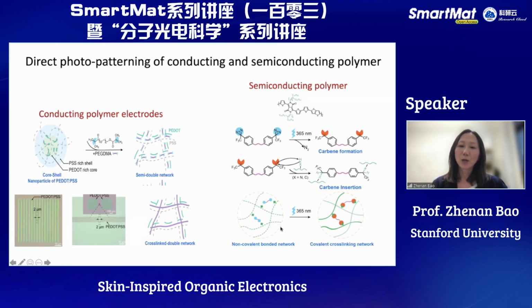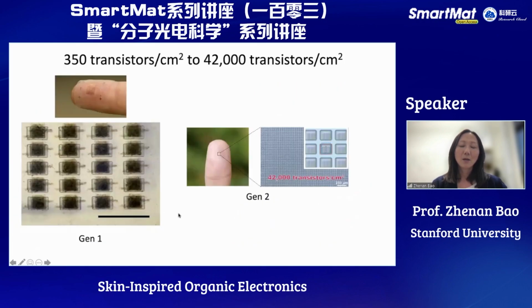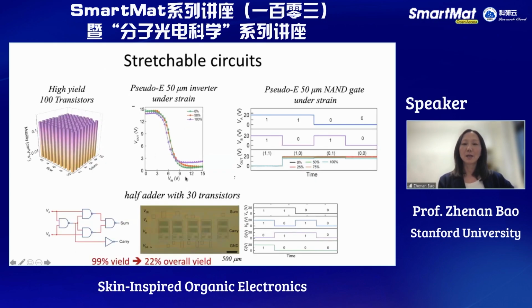And similarly, with the dielectric material, we used a similar patterning method. So this allowed us to decrease the feature size for both semiconductor and also, importantly, the electrode material, going from the first generation of 350 transistors per centimeter square now to 42,000 transistors per centimeter square, but with charge carrier mobility at amorphous silicon level.